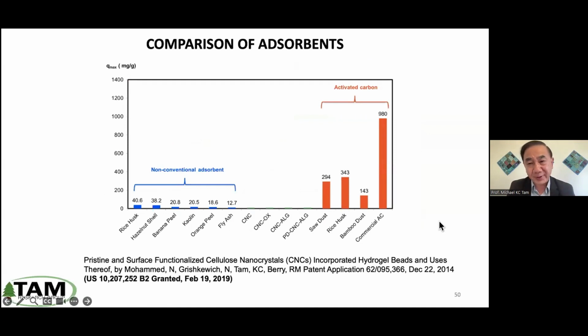So we want to compare to the gold standard, which is activated carbon. This is the most common method used to remove contaminants in water. They are very effective and very good, but they are produced by a high temperature process from many types of charcoal material, and that results in a lot of energy use and CO2 release. In many countries where they do not have access to this material because of cost, they use waste from agriculture like rice husk, banana peel, orange peel, but the performance is not as good, right? Cheap, but not as good. Very good, but CO2 release and also costly. So our material is green, has performance comparable to activated carbon, and is produced in water with a low temperature process. Our result shows that it can be another source of adsorbent for some of the contaminants found in water.